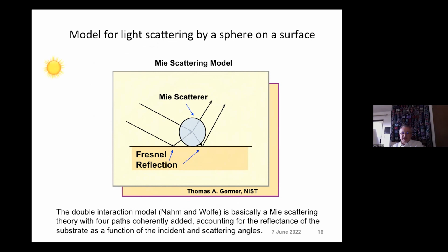So this is a little model put together by Thomas Germer of the National Institute of Standards and Technology. And he has a software, free software, that you can find at NIST, which is a Mie scattering model, a very complex model, in order to try to understand the scattering that I showed you before in the atmosphere, to apply that scattering to when a particle has actually deposited on a mirror for CSP or a PV module surface cover glass itself.